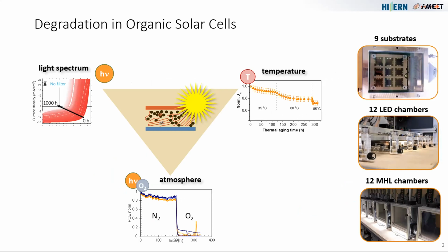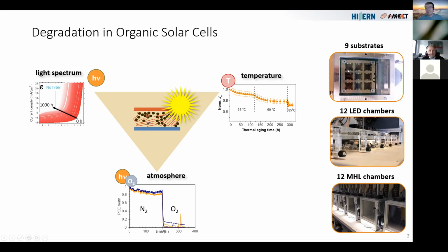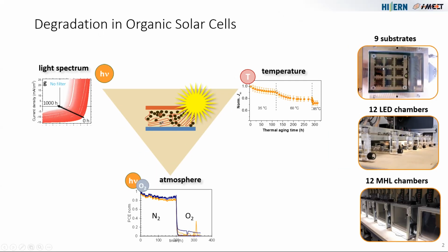First, what we have in organic solar cells is always different challenges for stability. Like, of course, light stability, where just the incident light can degrade the material. This often depends on the spectrum. Then temperature can play an important role, and of course, the atmosphere. We are using these degradation chambers here to control temperature and atmosphere. And then we're using different light sources that we put on top of these degradation chambers, like LED or metal halide lamps, to control the spectrum. And on top of that, we can also use cutoff filters to really zoom into a certain regime of spectral sensitivity.